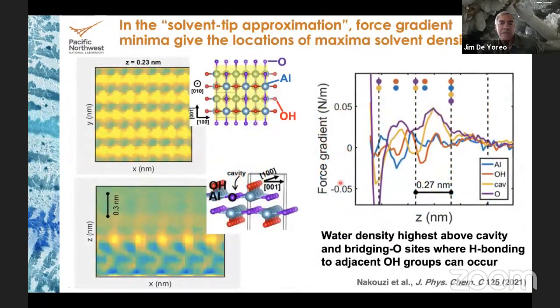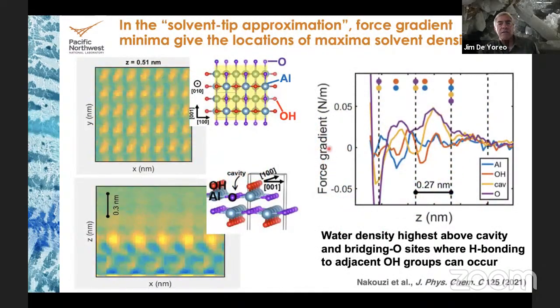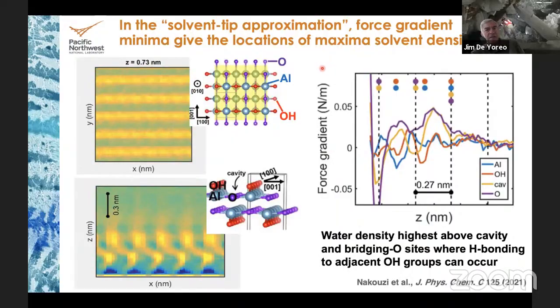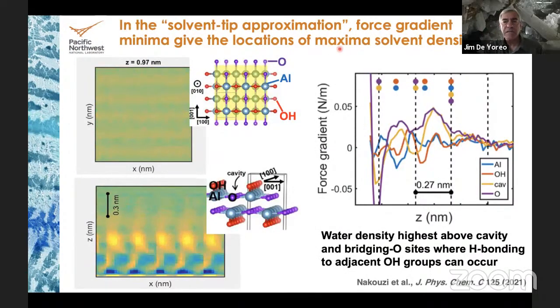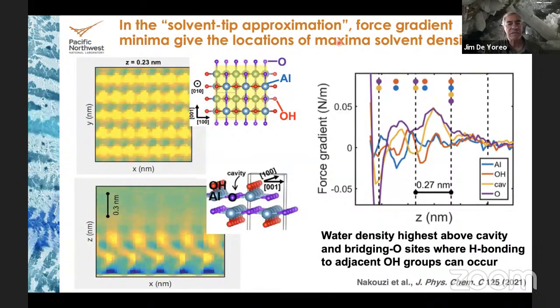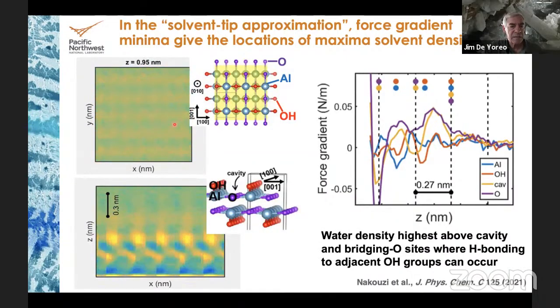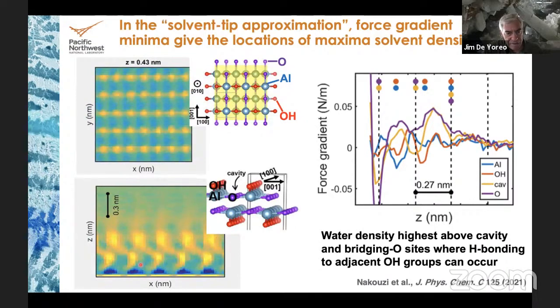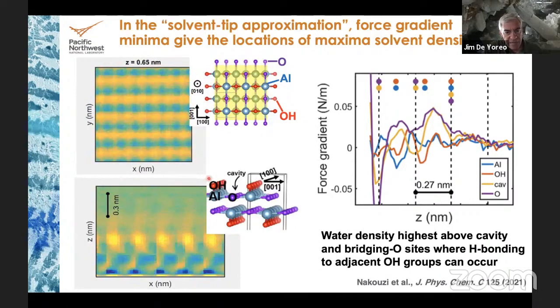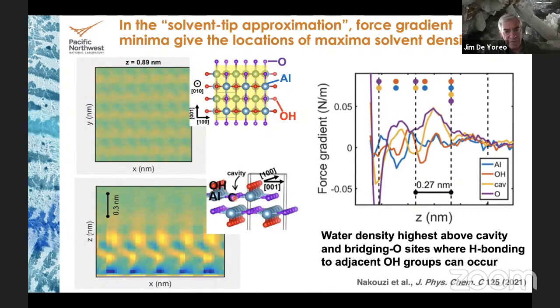So the idea is something called the solvent tip approximation, which says that the tip acts like a solvent molecule. And the places where you see minima in force gradient are the places where there's a maximum in solvent density. So this is coming up from the surface, and there are places where the solvent is high density and places where it's low density. Again, blue is high, yellow is low. As we go across the surface, you can see this oscillating pattern. That's because we're going up over OH groups, down into cavities next to oxygen sites, and so on.